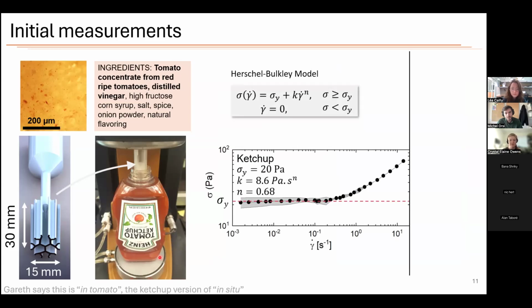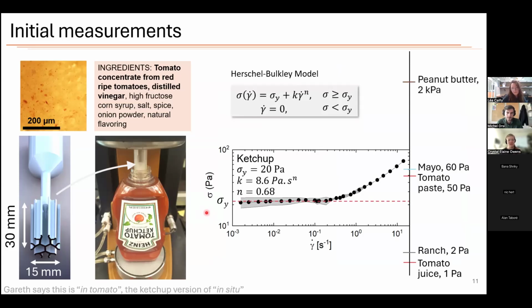And so going back to our Herschel-Bulkley model, we have a flow curve for ketchup here. And we find that the yield stress is about 20 pascals. To give you some context, tomato juice is about 1 pascal, ranch is 2, tomato paste is about 50, mayo is 60, then you have peanut butter, which is much, much higher, and then Oreo cream, which is 10 kilopascals. So ketchup is fairly flowable, but it has some noticeable structure.